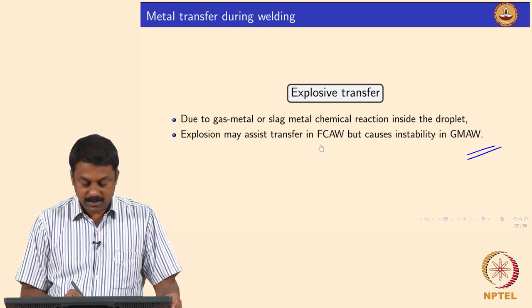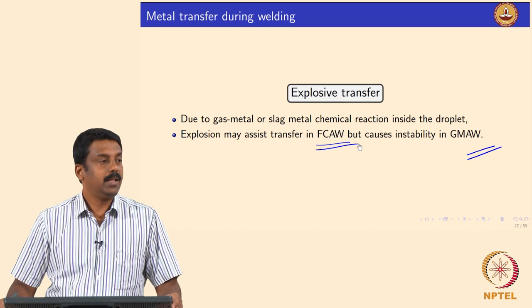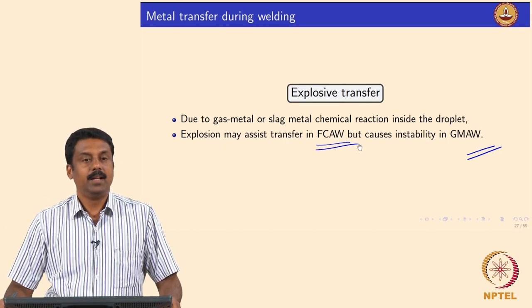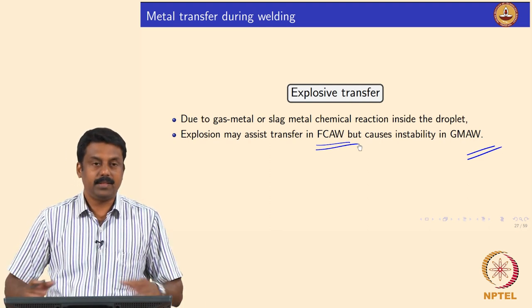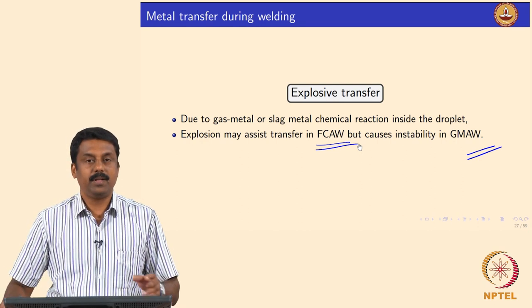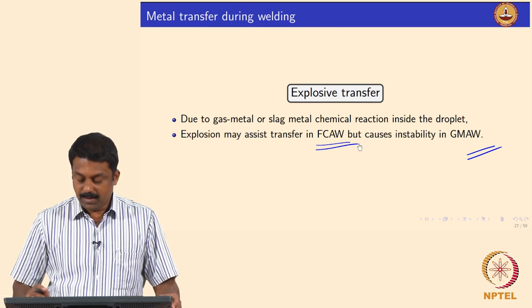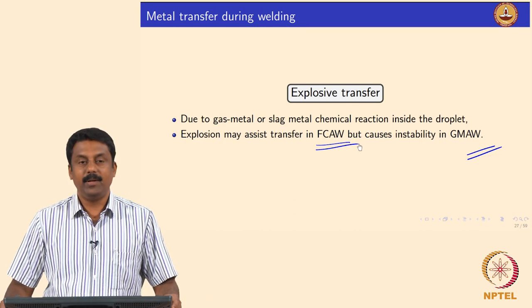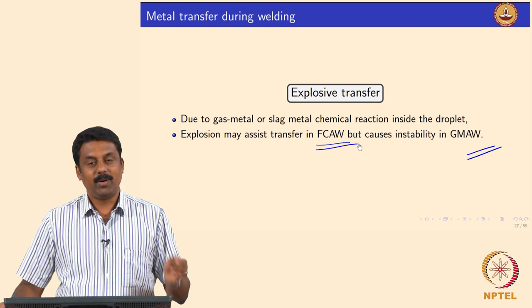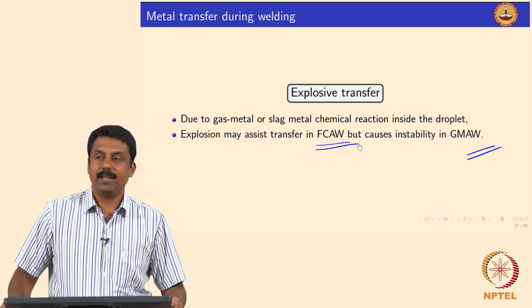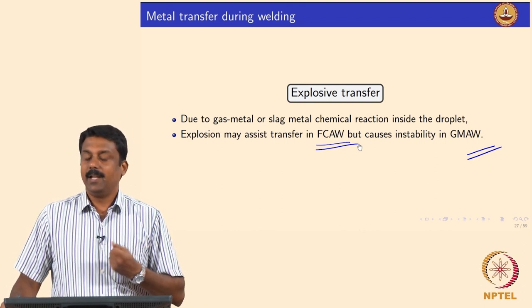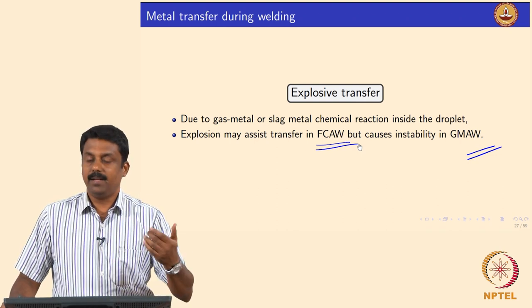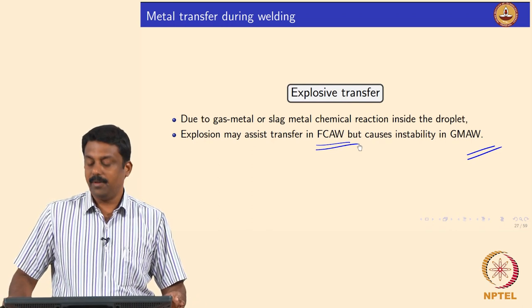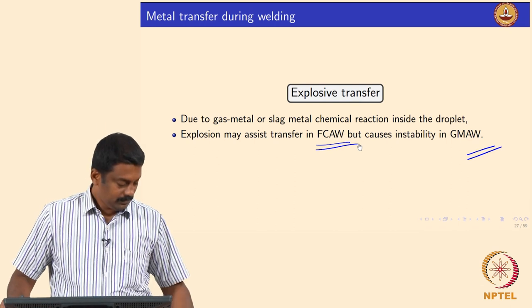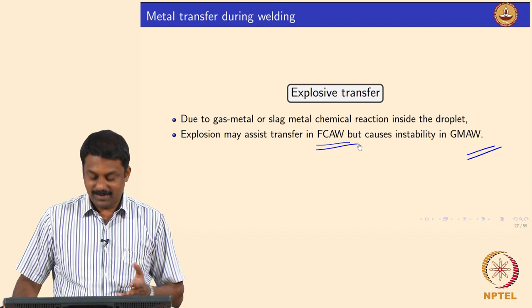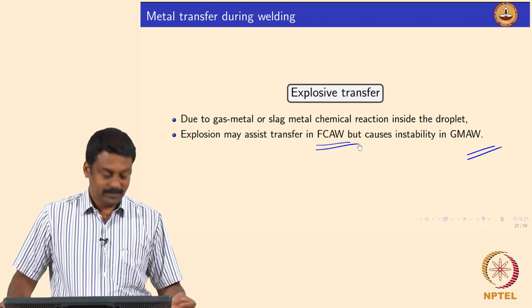In most cases, it is used for spraying or coating, if you want to deposit FCAW wire onto the substrate. You can use that, because you do not care where exactly the droplet is going. So you can do an explosive transfer by using high current and increase the productivity, but in GMAW it causes instability, because when you are welding, I do not expect a droplet to explode and go everywhere. You want the droplet to go to the weld pool, the cavity. If you are using FCAW or any other electrode to deposit a layer, a coating, then we can use the explosive transfer. Okay, it's clear. Unfortunately, I do not have any video for this, because we never managed to get that. We need a very high current for explosive transfer. Good.